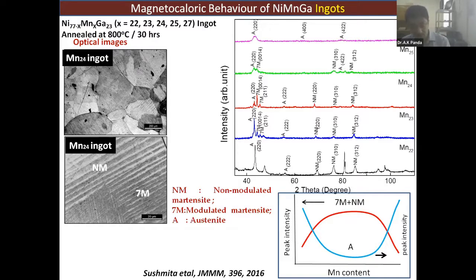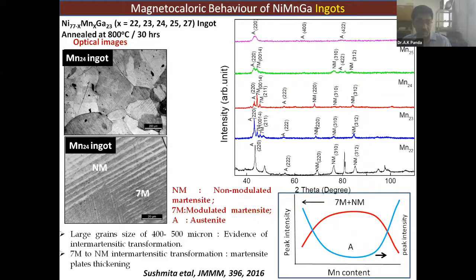Schematically, we are showing how the variation is. In the bottom right side, we try to show it schematically for a better understanding. At a very high manganese content, we have austenite. At a very low manganese content, we have some austenite in combination with non-modulated martensite. At an intermediate manganese content, you have a lot of non-modulated and modulated martensites. That is how this is structurally characterized, and that will also be evident in your caloric properties.